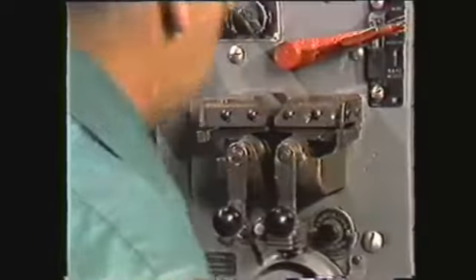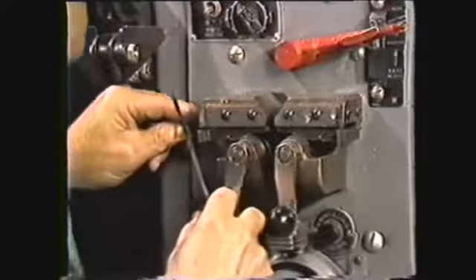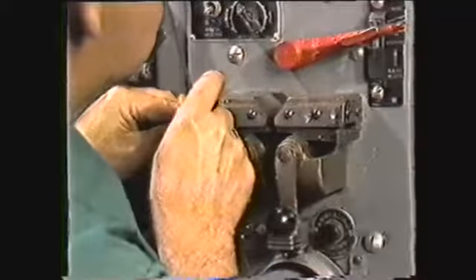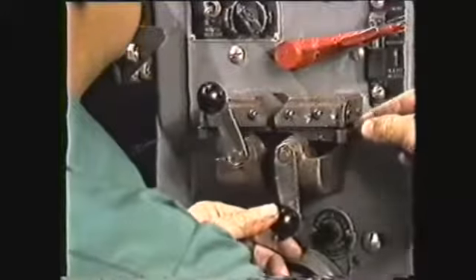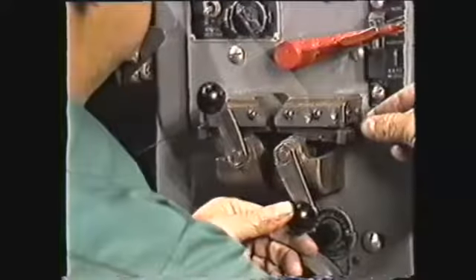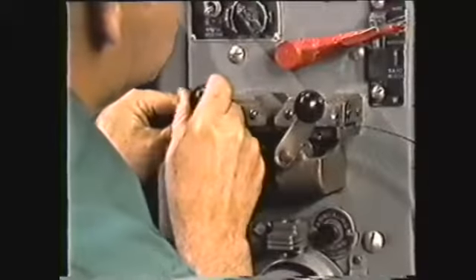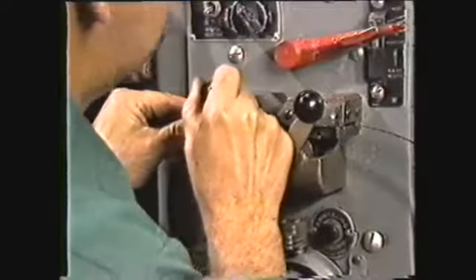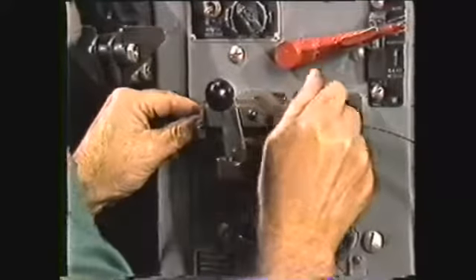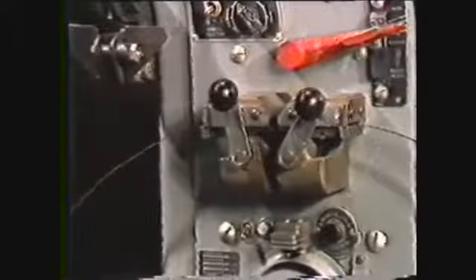Clean the jaws and place one end of the blade in each jaw. You should be especially careful that the blade is properly aligned in the jaw and the back of the blade aligned with the guide in the back of the jaw. The blade ends should extend approximately 1/2 the distance between the two jaws. Tighten the blade clamp and recheck to see that the blade ends are not offset or overlapping.